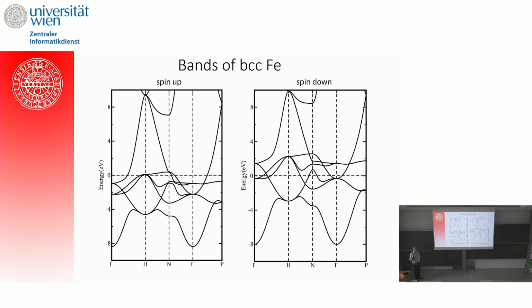But in terms of ground state properties, you don't have to worry about the fact that you can't compare these energy bands to measurements. DFT tells you that cohesive properties and ground state properties are still available to you via the density functional. In this particular case, if you're interested in magnetism, all you have to do is occupy a number of spin-up states up to the Fermi level, and occupy a number of spin-down states up to the Fermi level, and then multiply with the g factor of 2, and voila, you have a magnetic moment of BCC iron that agrees very well with experimental data.